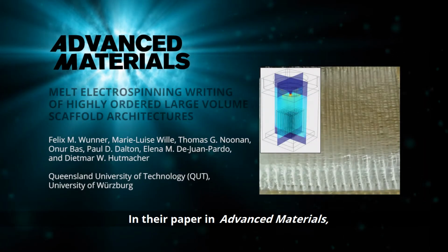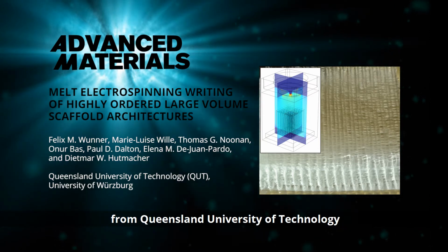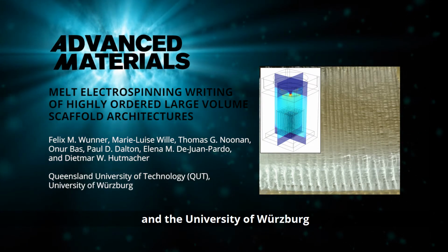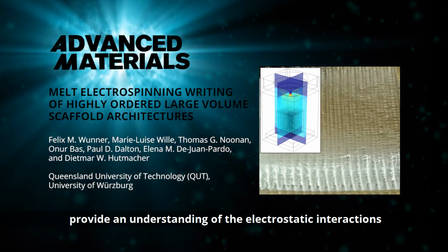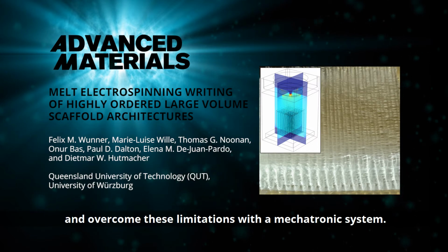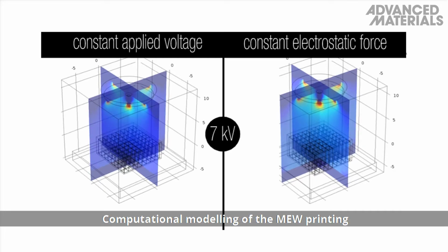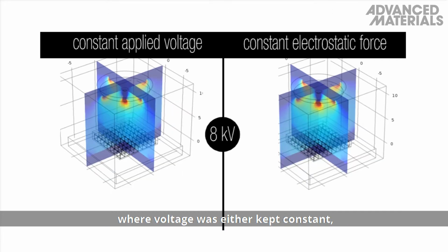In their paper in Advanced Materials, Professor Dietmar Hutmacher and colleagues from Queensland University of Technology and the University of Würzburg provide an understanding of the electrostatic interactions that currently limit scaffold size in MEW and overcome these limitations with a mechatronic system. Computational modeling of the MEW printing environment was undertaken, where voltage was either kept constant or altered